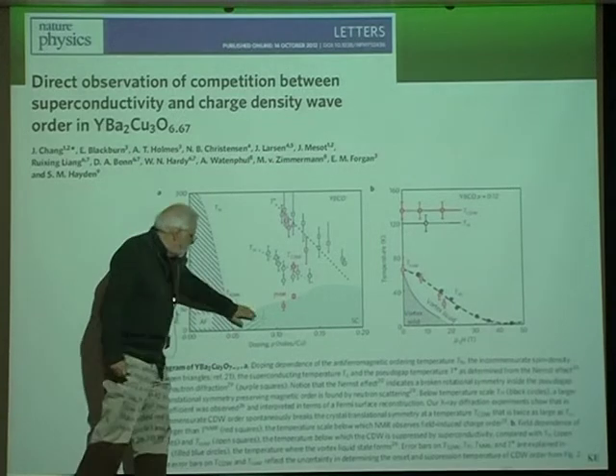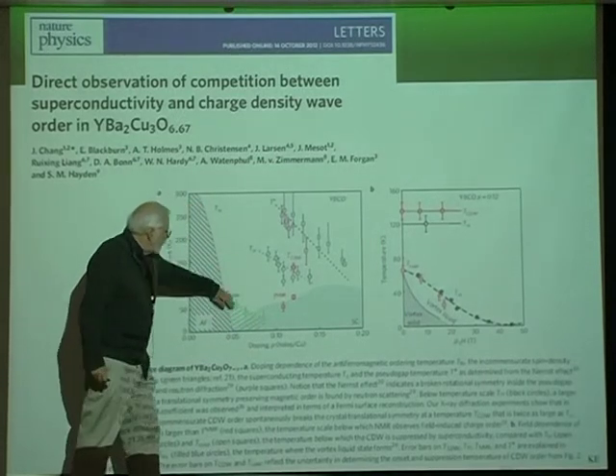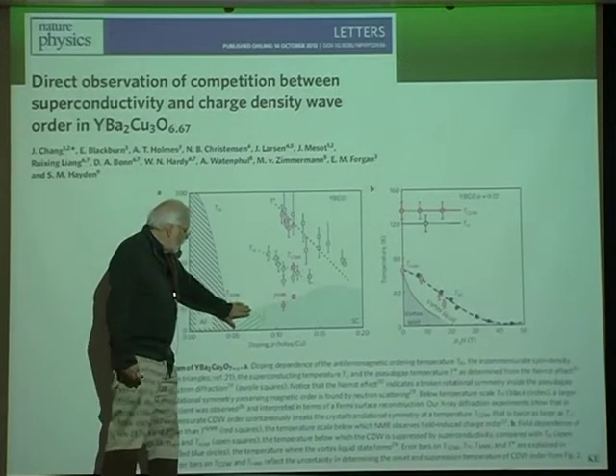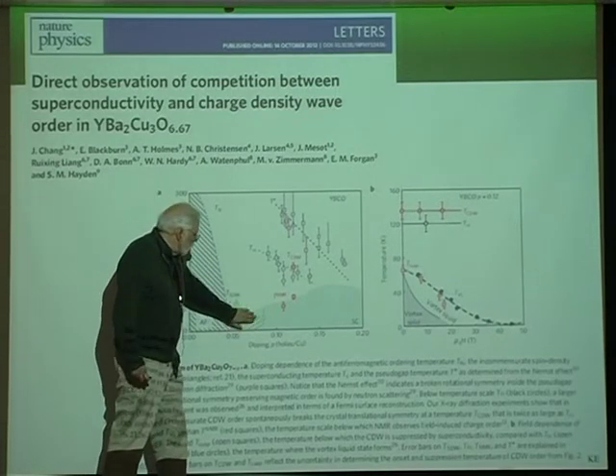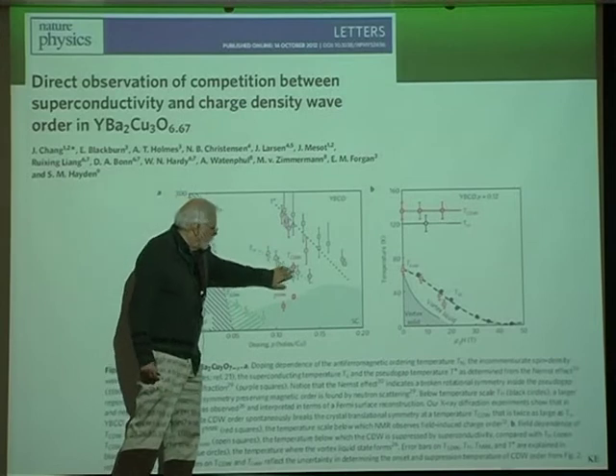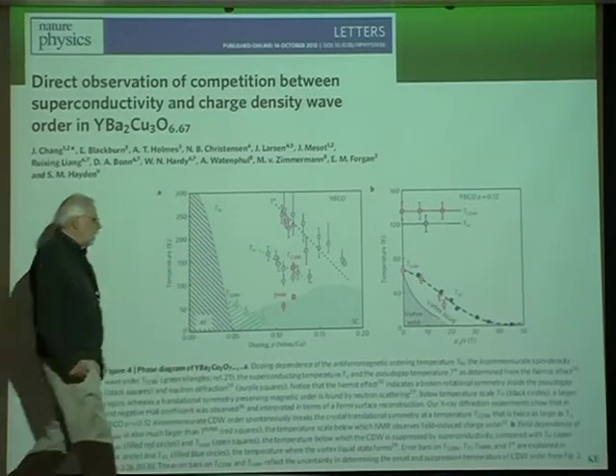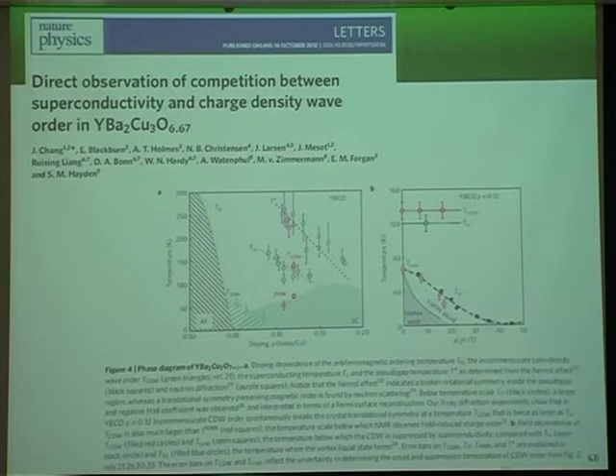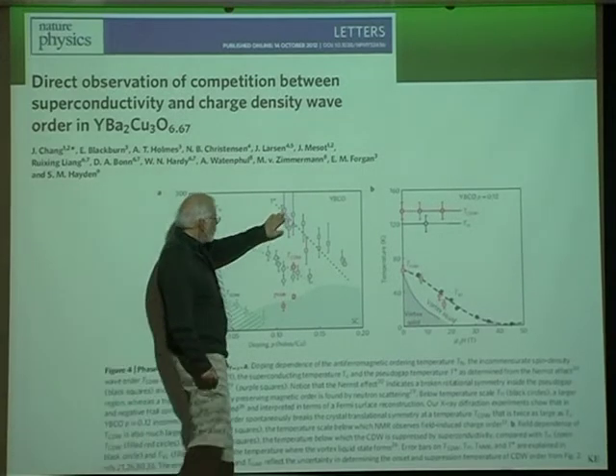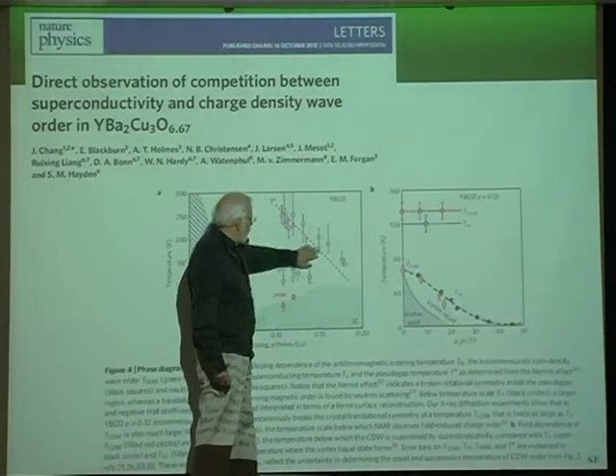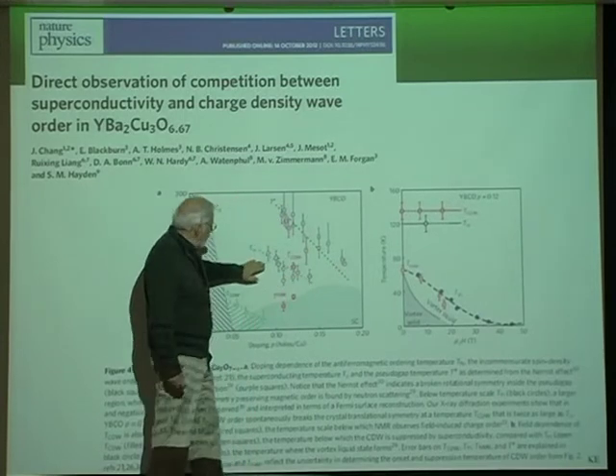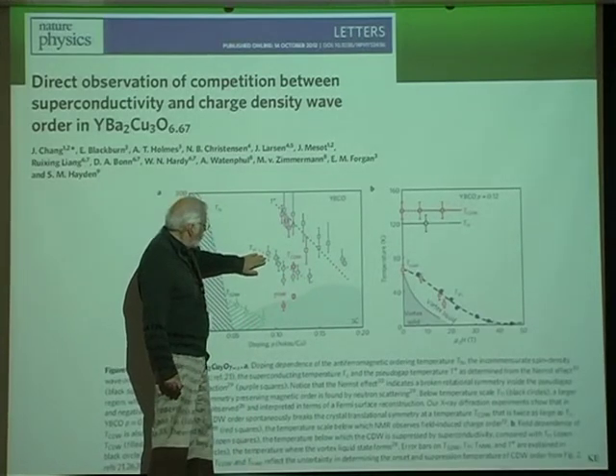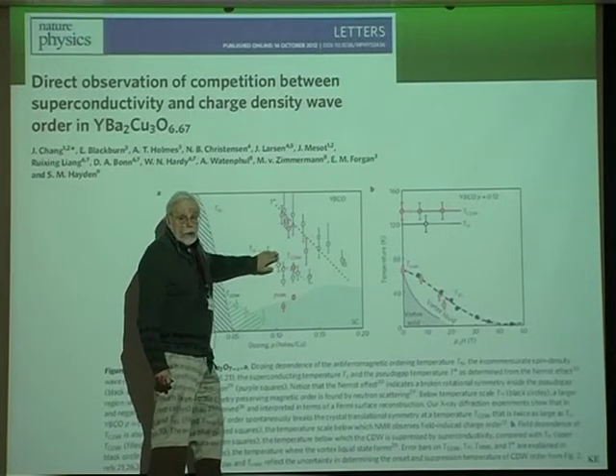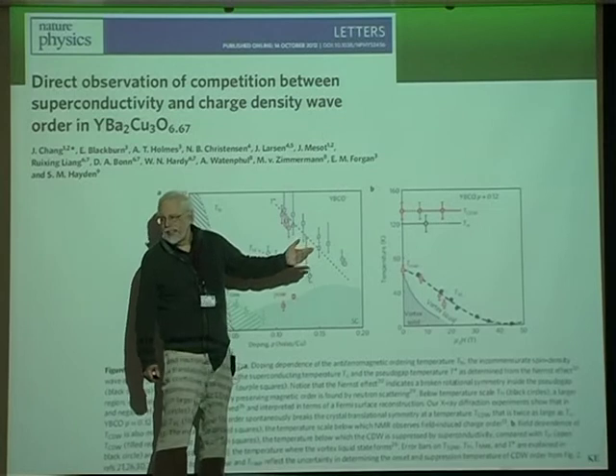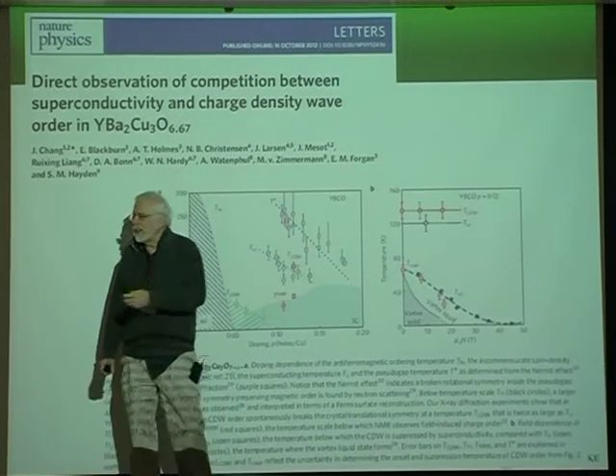And the spin waves are in this region. So here there's some spin excitations at low frequency. Here it is a charge order that occurs in this region. And T star, so the pseudo-gap temperature, I will talk about it later. Again, in the hole-doped cuprates, this is not where the transition occurs. But it could be a precursor, in the same way as in the case of antiferromagnetism.